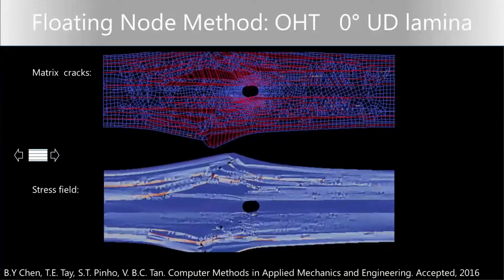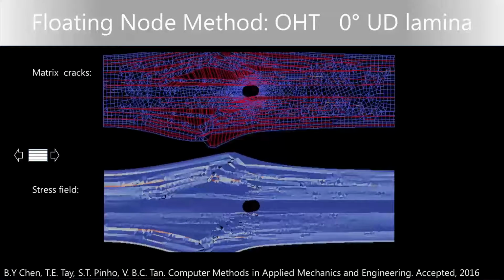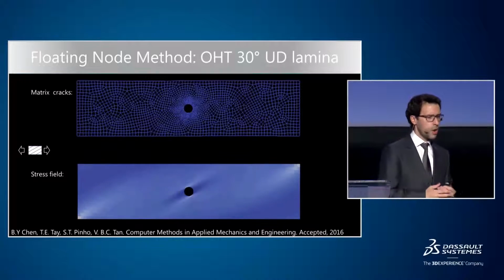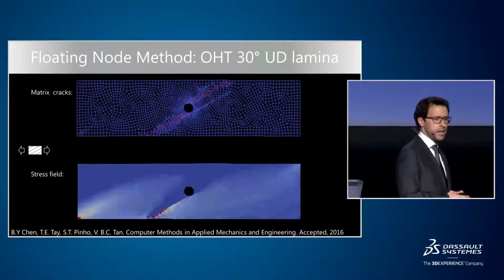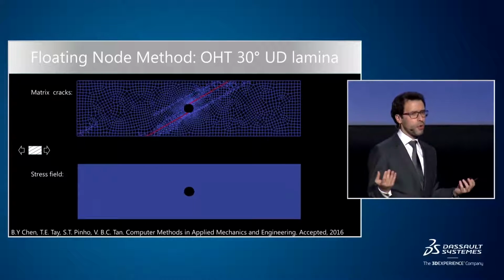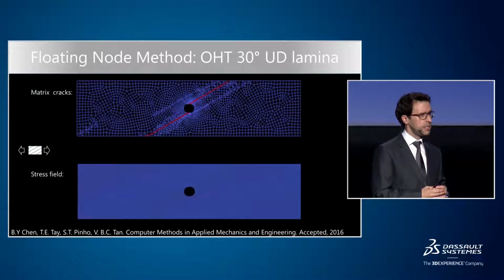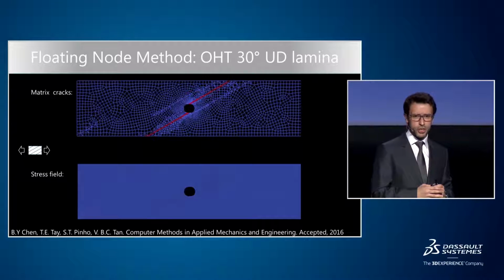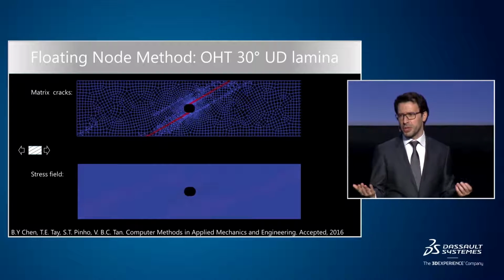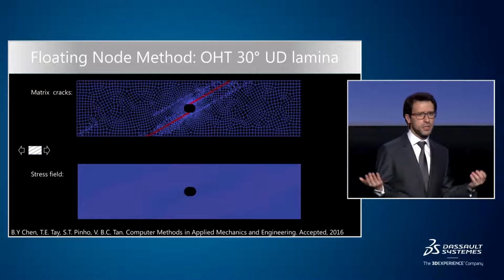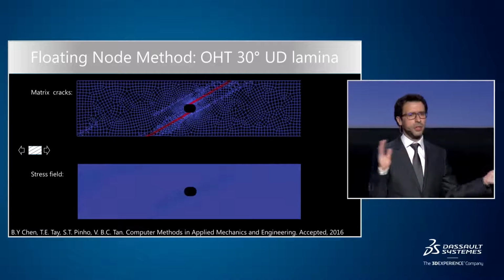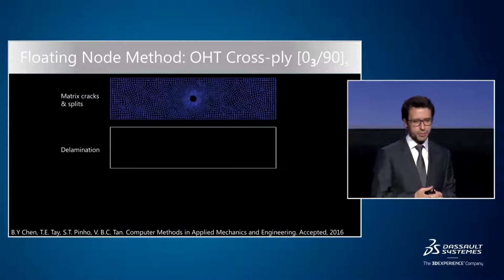So now I'm going to show you another example in which the fibers are at 30 degrees. So that will affect the direction in which the cracks can grow. And it will also affect the number of cracks that you get in your specimen. In this case, as soon as these 2 cracks got completely formed, the stress field becomes uniform and nil because you cannot transfer any more load between the left and right sides.